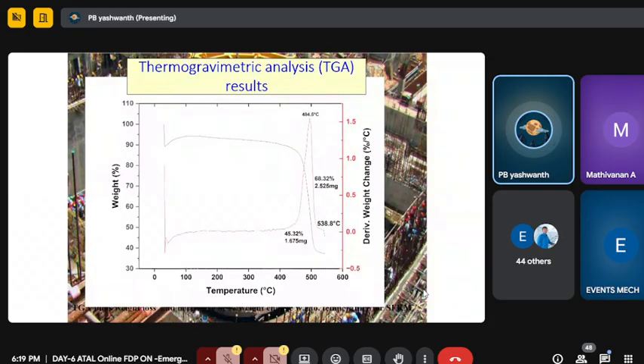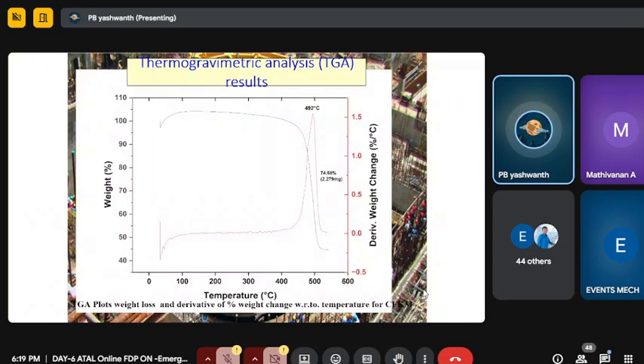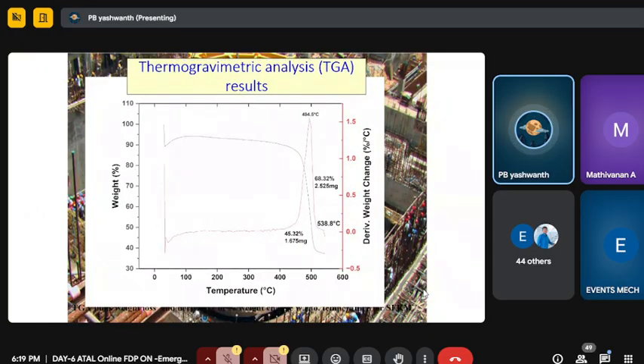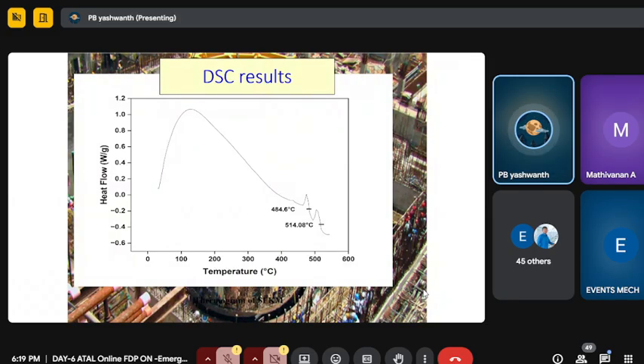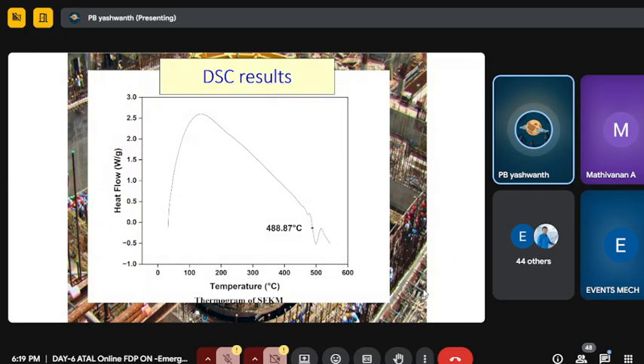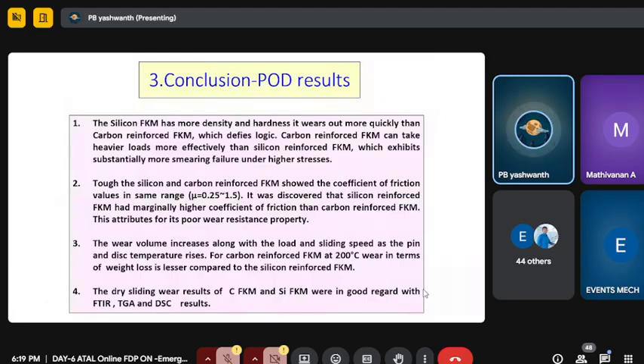Comparatively, when you see the previous one and the other one, it was varying by just two degrees. When you plot it alone, you can see the gap. It has two slopes in the differential scanning calorimetry, whereas this had only one slope. We want to conclude the pin-on-disc results of the fluoroelastomers.